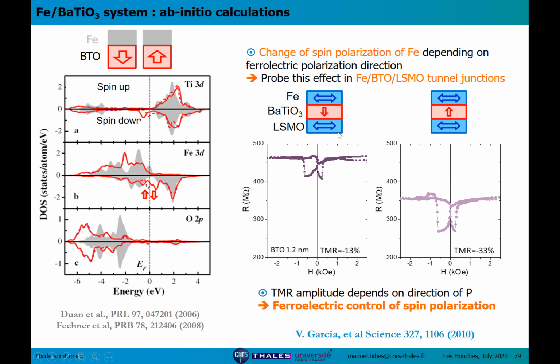So we use this junction, iron, barium titanate, LSMO, which I've shown you before, and then we cool down to low temperature and we measure the TMR, and we get negative TMR, because iron has a negative spin polarization at the interface with barium titanate. And you can see that not only do we have a shift of the resistance value, so this is tunnel electroresistance, but also we have a change of the value of the TMR. TMR is about 13%, here 33%. And this reflects, we think, this prediction from Tsymbal, which is the ferroelectric control of spin polarization.